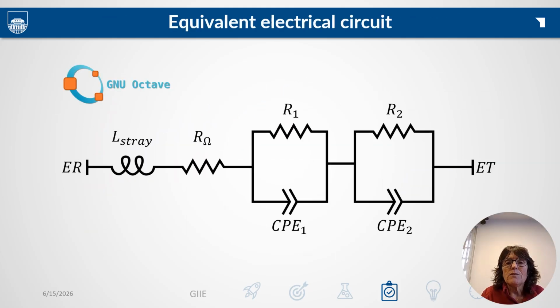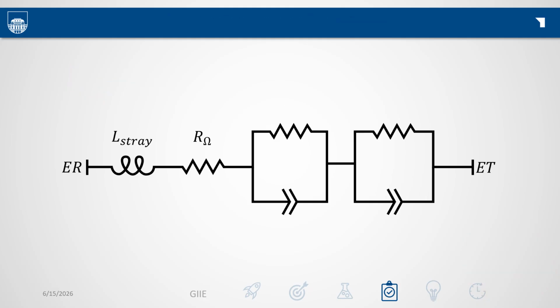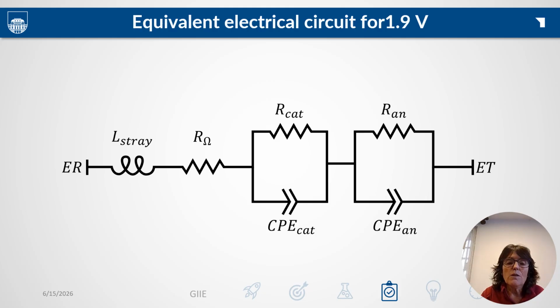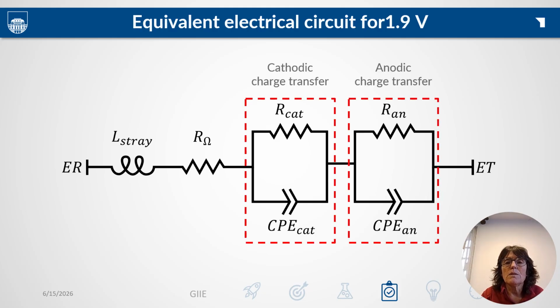To separate the different contributions, we fit the EIS spectra to equivalent circuits at 2 operating points, 1.9 volts and 2.3 volts. At 1.9 volts, where the response is controlled by activation overpotential, we use a simple circuit with 2 resistance-constant phase element branches, one for the cathodic charge transfer and one for the anodic charge transfer, in series with the ohmic resistance and the inductance.